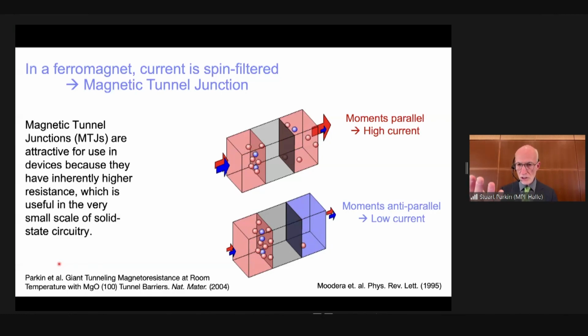In this concept, as shown in this schematic cartoon, you can see, again, we have two magnetic layers, shown by their directions, red and blue, but the gray region in between the layers is no longer a metal like copper, it's actually an insulator. And the electrons have to quantum mechanically tunnel from one magnetic layer through the tunneling barrier into the opposing electrode. When the magnetic layers are parallel, the electrons that are extracted from one surface will automatically be spin polarized. This is because in a ferromagnet, the number of electronic filled states at the Fermi level is distinct for spin up and spin down electrons. The symmetry is broken by the magnetic moment of the system.